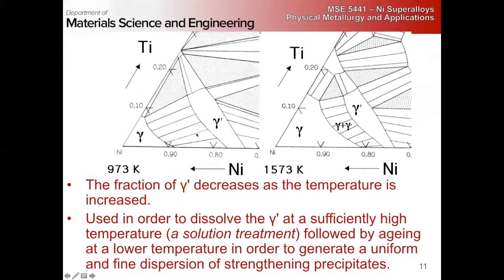One thing we do have to pay attention to: for the same composition, as we go up in temperature, the extent of the two-phase field decreases, and so the relative fraction of gamma prime tends to decrease as we go up in temperature, right? This is handy from a processing point of view because we can dissolve the gamma prime, giving it a solution treatment to homogenize the composition, and then give it an aging at a lower temperature to try and generate a uniform fine dispersion of the gamma prime. But it also puts an upper limit on the operational temperature, because we don't want to dissolve away our gamma prime in service.